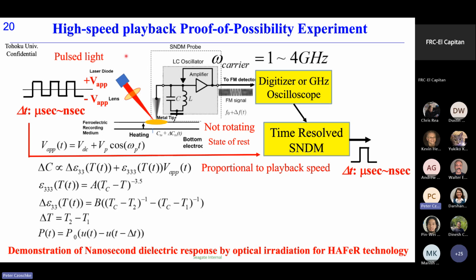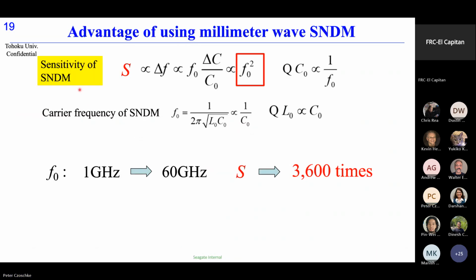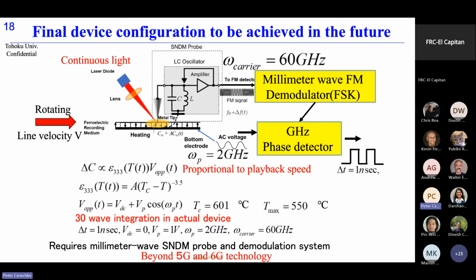So we'd like to surely confirm that the nonlinear dielectric response can be detected in principle. So we conducted a high-speed playback proof-of-principle experiment. And in this case, we cannot obtain the millimeter wave probe, so we use the usual 1 to 4 gigahertz probe. And instead of using a rotating periodically poled medium, we measure a non-rotating material. In this case, continuous light is sufficient, so we don't need a pulse light.